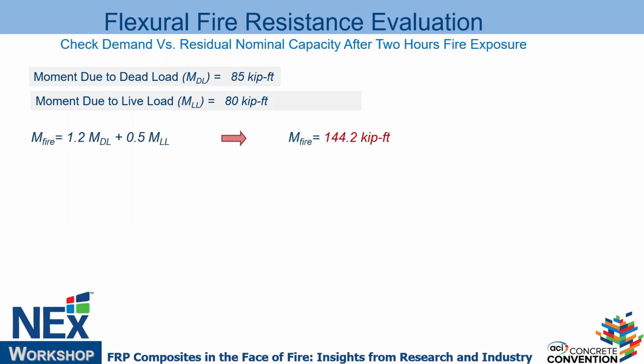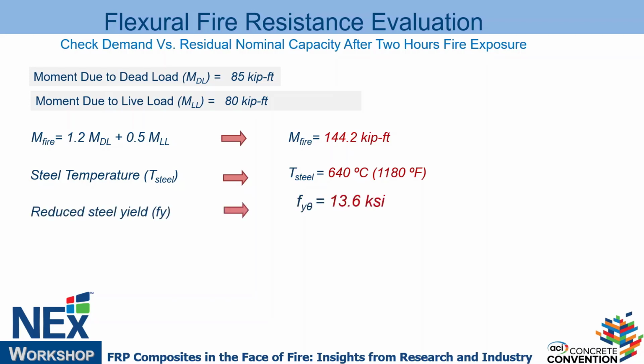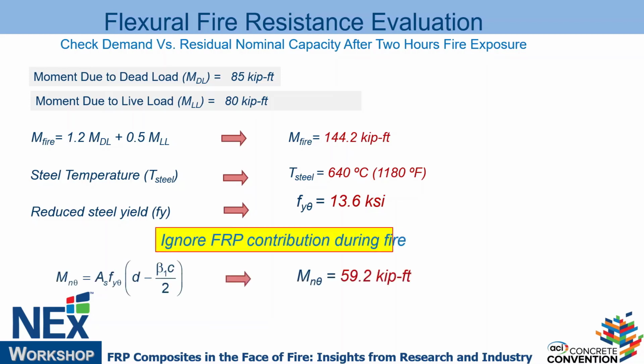So when you go through the load combination, during fire, the demand is 144 kip-feet that I need to withstand during fire, right? When we run the calculation for those bars, you can see that the corner bar rises to almost 1200 degrees Fahrenheit, 640 C, right? At that temperature, the curve is very sharp, and the yield drops significantly. This is less than 25% of the capacity of the steel bar. So they would not really pass. And even if we ignore the FRP contribution, this would be the capacity, close to 60 compared to the demand of 144, which would not work, right? So this is an element that would not work.